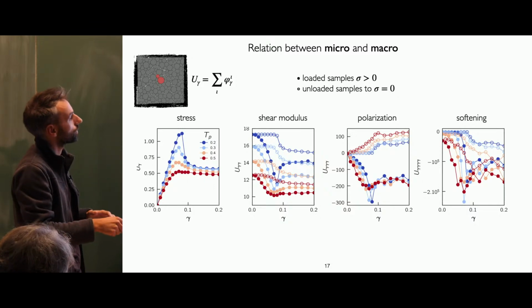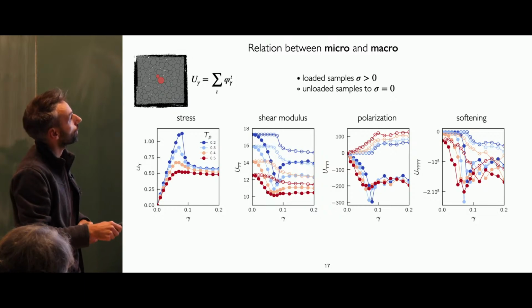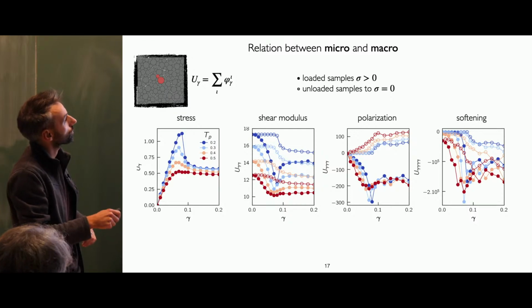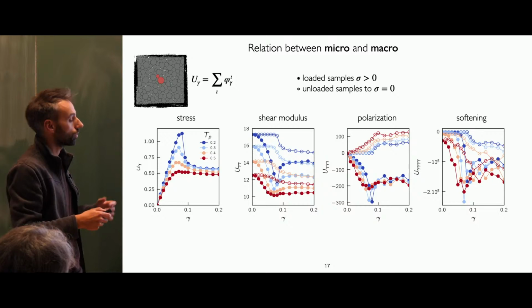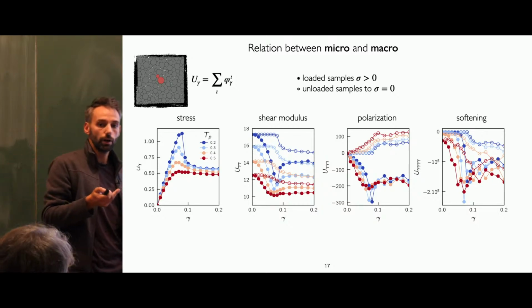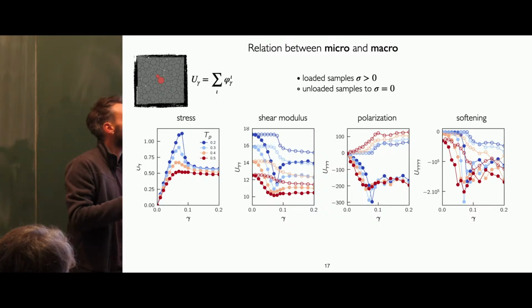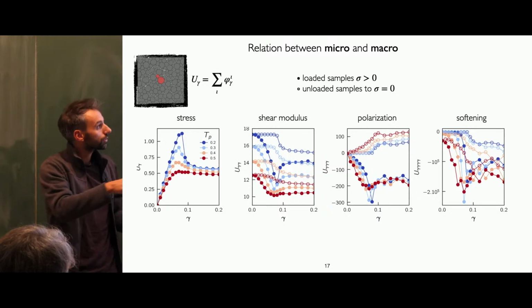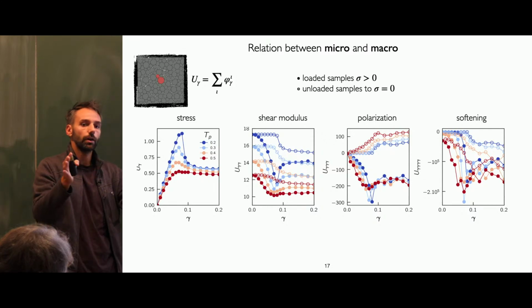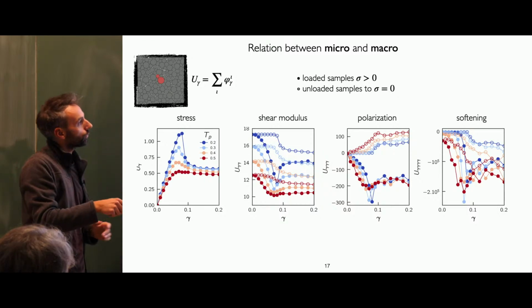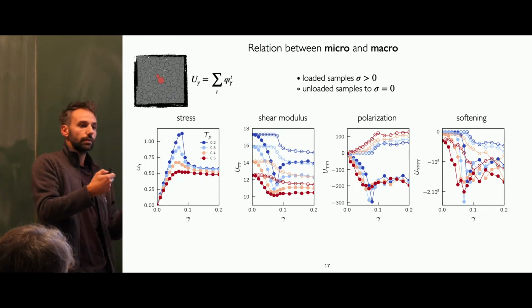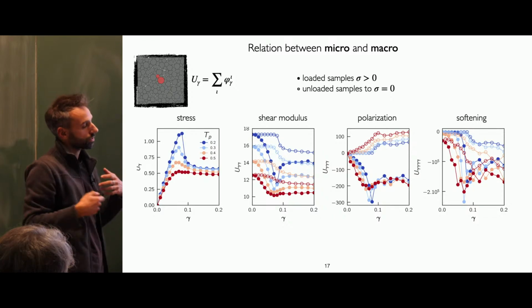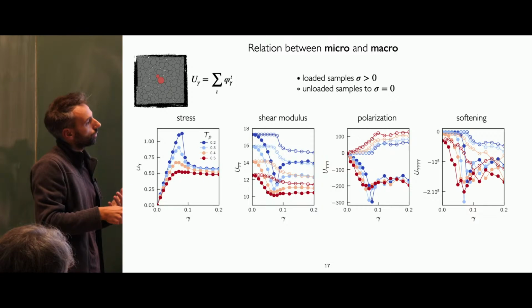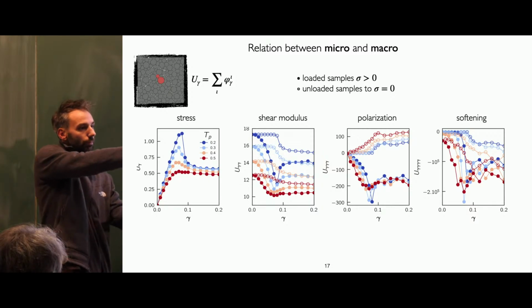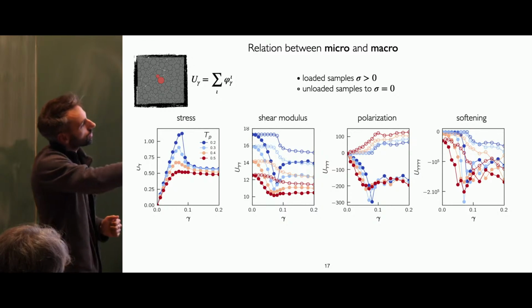So that's a lot of information, so I will not go into detail, but one interesting one, for example: the first coefficient is just the stress, the second is the shear modulus, and then you have some nonlinear terms. The third coefficient is the one which is the odd power of the strain. So that will give you information about polarization. If you take a glass and you just quench it, this coefficient will be 0 because you didn't do anything to your system, so there is no way that you will deform differently if I shear it positively or negatively. But when you start to shear your system, you will activate plasticity that commensurates with the deformation, which means that you really have a mechanical history, in the sense that if you take your system after a lot of plasticity and unload the stress by just deforming it back a little bit, you will see that now this coefficient is not 0 anymore, it's positive.